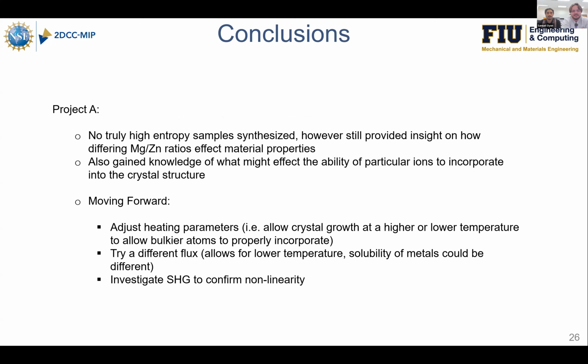For Project A, as Sam mentioned, we didn't get any truly high entropy samples synthesized, as most of that phase was lost in the polishing process. However, we were still able to gain some knowledge and insight into the effects of changing magnesium to zinc ratios and how that affects the band gap in the material. And moving forward, we think it would be good to adjust some of the heating parameters, maybe try a different flux, just to help those larger atoms incorporate a bit better into the crystal structure.